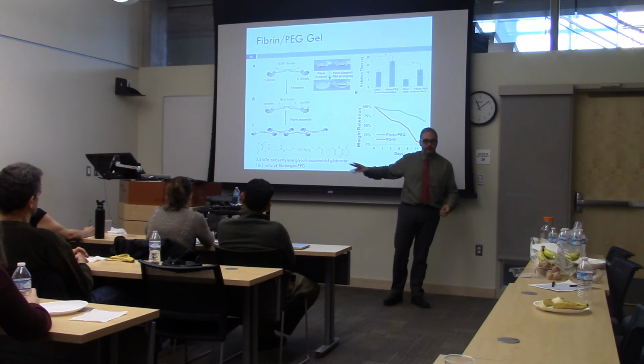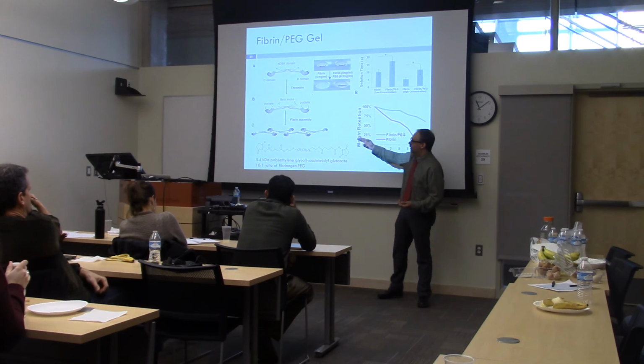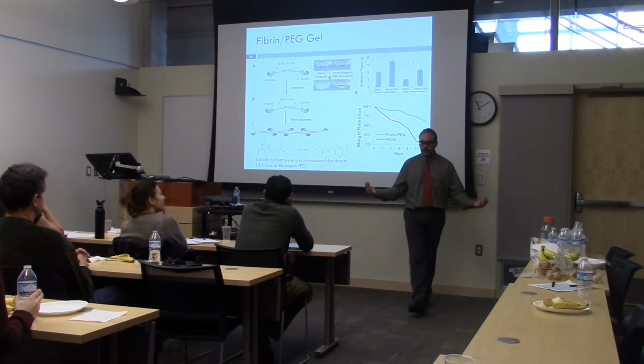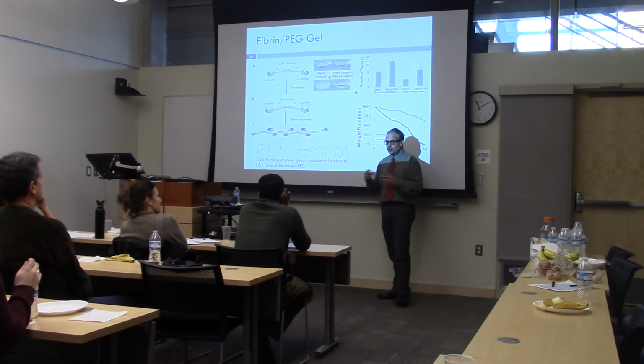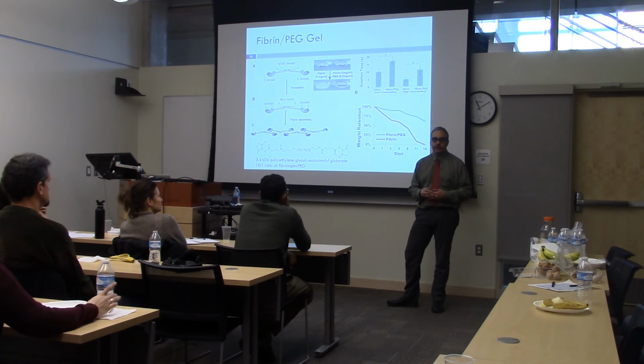And we found that fibrin, so fibrin is a component that makes blood clots in the body. It starts off as inactive fibrinogen, and when that fibrinogen encounters thrombin in the presence of calcium, it cleaves to fibrin, fibrin self-organizes, it can form a blood clot, it can also just form a gel that encourages blood vessel growth into it. You take these fibrin gels, you can get open lumen through them with endothelial cells. However, the endothelial cells, if you put them at a high enough concentration that it would really be physiologically feasible to use it, also secrete proteins that just chew up an entire fibrin gel. And so you don't end up with a tissue, if you're only using vascular cells, you just kind of end up with mush.